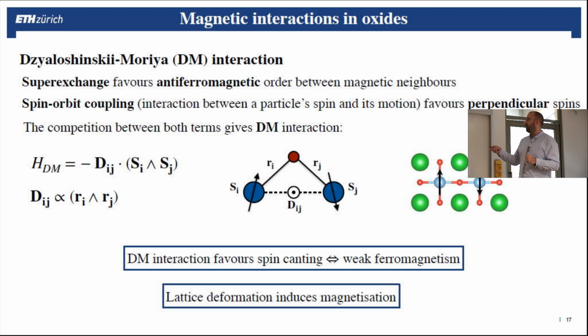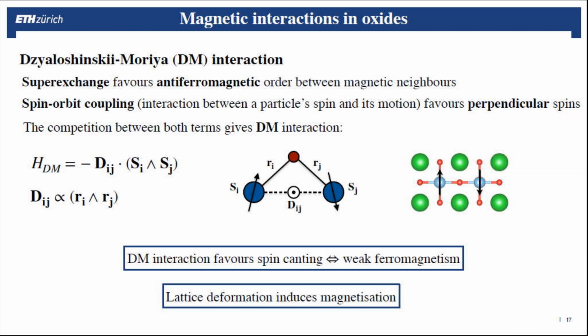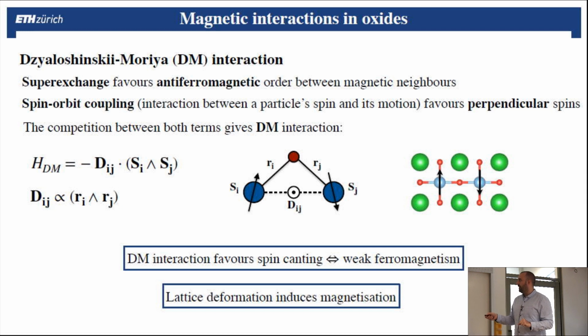Another interaction I will tell you about is called the Dzyaloshinskii-Moriya interaction. So we saw that super exchange, just what we saw before, favors antiferromagnetic order, so opposite spins. Then there is something called spin-orbit coupling, and a simple way to see it would be the interaction between a particle's spin and its own motion. And this coupling usually favors perpendicular spins, so 90 degrees. But when you combine both together, you have this interaction called Dzyaloshinskii-Moriya, which can be expressed in this way. And I will just decompose it.